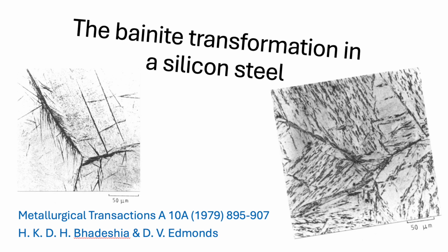It really has. And you mentioned it's the least understood transformation. Why exactly? It just forms in this really awkward temperature window. It's cooler than where ferrite or pearlite form, which are definitely slow diffusional processes. But it's hotter than where martensite forms, which is this incredibly fast, almost purely mechanical shear transformation. Bainite's stuck in the middle. So that awkward middle ground, that's where the argument lies then. Is it fundamentally diffusional, like Widmanstätten ferrite growing with these little atomic ledges? Or is it fundamentally displacive, like a shear transformation that maybe just lets the carbon atoms sort themselves out later?